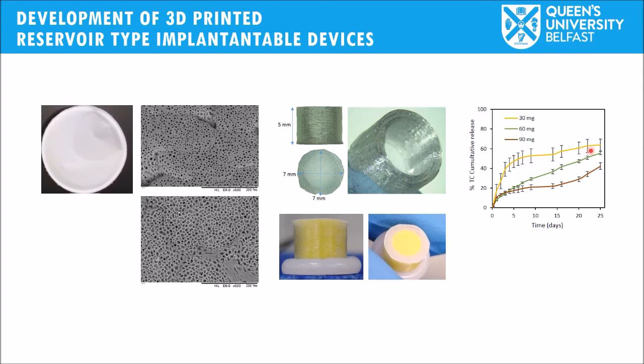This can be helpful, for example, to prevent infection after surgery, and by modifying the drug loading, the amount of drug inside the implant, the release profiles can be altered. We have quite sustained delivery whenever the drug loading is 60 milligrams, but this tells us that the membrane is capable of sustaining the delivery of hydrophilic molecules again, and we can use 3D printing to quickly prepare some prototypes on top of those membranes.